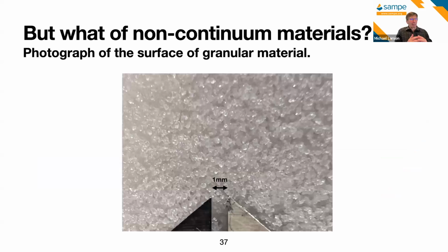And we further did some testing with that particular specimen, and we tried a whole host of materials. One thing we found is these days people are finding that non-continuum granular materials are finding more and more applications, because these can be tailored by changing the density, by changing sintering pressures and temperatures when manufacturing, so that we can get functionally graded materials that can be compliant where we need compliance, say at the edge of our structures, and be more consolidated, stronger, and stiffer in other places.